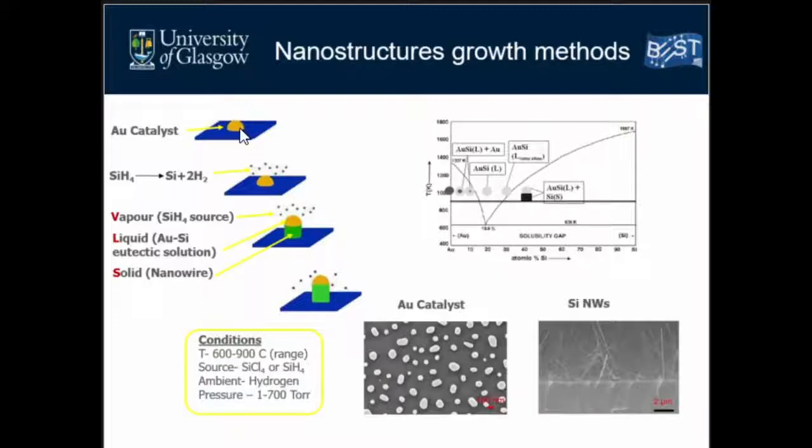So what it does is, initially you have a catalyst particle, whose size will define the size of the nanowire we are going to grow. Then you take it to a high temperature where you expose it to the appropriate gaseous sources, silicon or germanium or gallium or aluminum, anything we want to grow. Those will decompose only at the specified locations of the catalyst particle and will precipitate preferentially between the catalyst particle and the substrate. So what will happen?